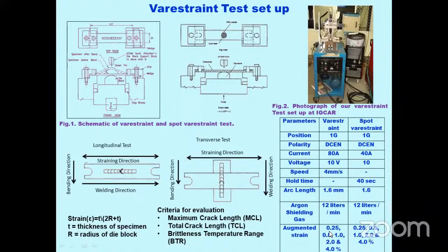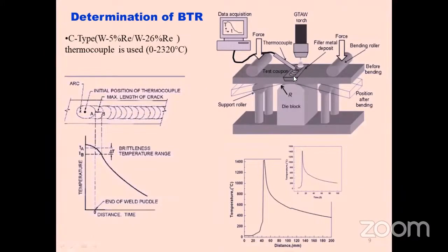So next is the way to determine when the experiment is completed. The hot cracking Varestraint experiment is completed. We again load the specimen, a normal, untested specimen, using the same parameters that we used for the Varestraint test, and we lay an autogenous weld bead over the specimen. While the weld is happening, we insert a thermocouple connected to a data logging system. By the time the thermocouple is inserted in the fusion zone, the arc is switched off. Here we are not going to apply any strain using the die block. And from this thermocouple, we are measuring the thermal profile of the cooling weld metal.